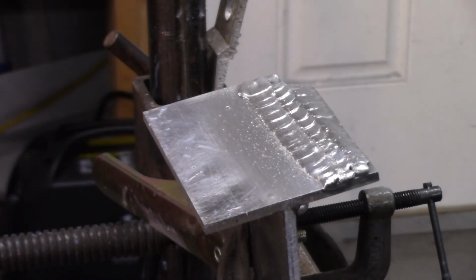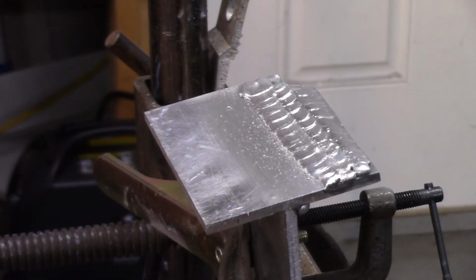When aluminum welds fail, it is usually due to cracking of some type. When you are finishing up the weld bead, you should take extra care to fill in the small crater at the end of the bead. This can be easily achieved by reversing your travel direction when you reach the end of the weld joint.